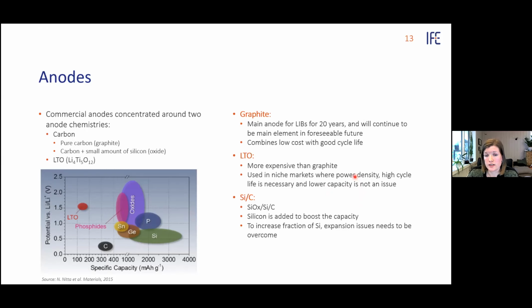And of course, silicon carbon composites are becoming more and more common. We have already quite some percentage of silicon oxide together with graphite in a few of the batteries, but we're seeing that this silicon content is increasing. Silicon is added to boost the capacity, and the expansion issue still needs to be overcome before we can introduce it much more.